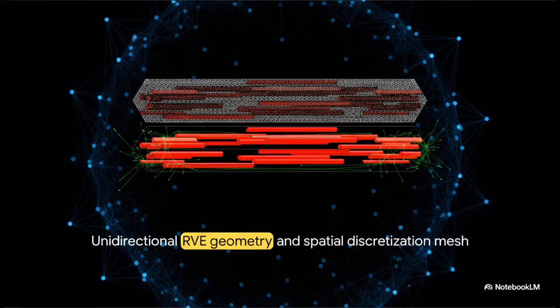Now, Figure 2 brilliantly illustrates what Step 1 actually looks like in practice. It shows the geometry and the highly detailed spatial discretization mesh of those unidirectional RVEs we just talked about. Notice the very specific geometric scaling they used here to guarantee statistical representativeness. The RVE length is scaled to exactly twice the fiber length, and the transverse dimensions are scaled to 5 times the fiber diameter. They ran all these analyses assuming perfect bonding between the matrix and the fibers, and they applied periodic boundary conditions just to capture the true, pure, homogenized properties of this unidirectional block.